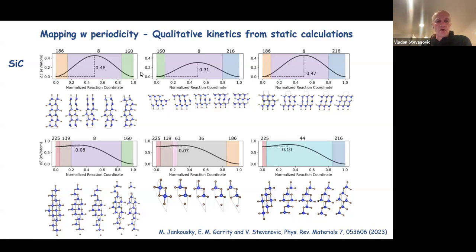And the energy difference, you are right about that. So the tetrahedrally coordinated polymorphs are actually very close in energy to each other. It's a well-known fact that every zinc blende semiconductor you could grow as a wurtzite, and it is a stable phase, it's not a problem. Or every wurtzite can be grown as zinc blende and this rhombohedral, and they live, whereas the rock salt seems to be a short-lived high pressure phase.